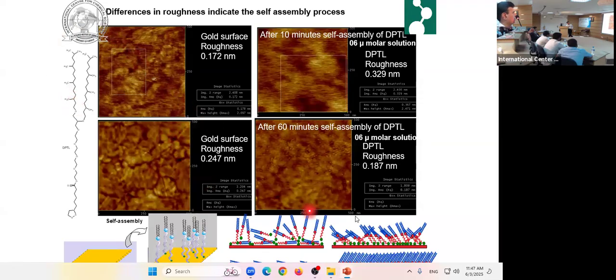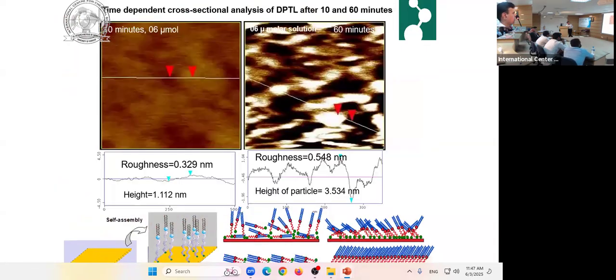But when we added this after 60 minutes, as you can see, these were filled by the DPTL molecule, and the roughness decreased, which shows that the surface is changing like this. With atomic force microscopy we were monitoring it, and after 60 minutes we observed these big particles. Their height is 3.534 nanometer, which exactly matches the height of our DPTL molecule. So it shows it is undergoing this process.